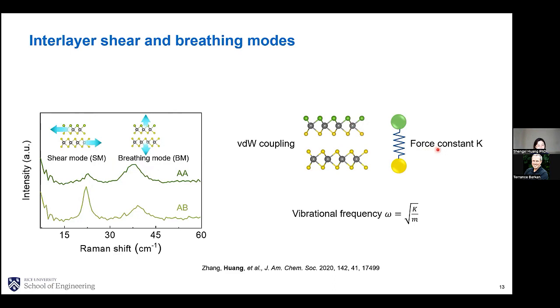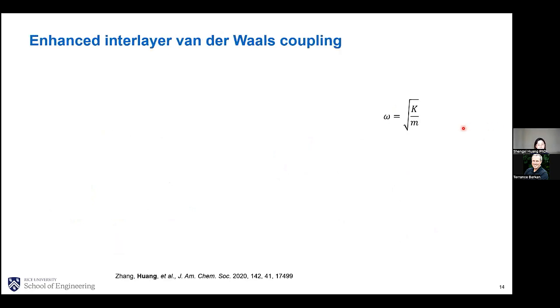In the linear chain model, we know the vibrational frequency can be calculated using this equation. Here M is the reduced mass of the 2 balls. Now coming back to this bilayer 2D material, the van der Waals coupling will correspond to this force constant. So we can use the vibrational frequency measured using Raman spectra and the reduced mass of these 2 layers to calculate the van der Waals coupling strength K. So let's do this. This is our equation.